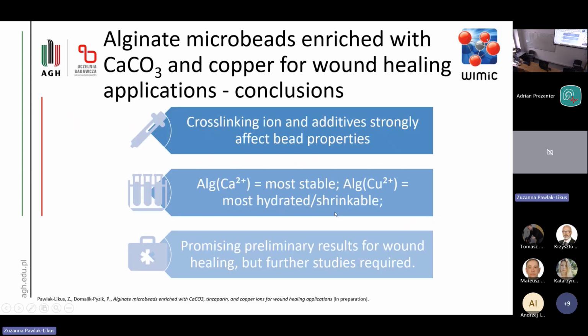So the conclusions that we took from those results are that the cross-linking ion and additives strongly affect bead properties. As we can see, the alginate that was cross-linked with calcium was the most stable, while alginate that was cross-linked with copper was the most hydrated and shrinkable formulation. So those results are promising for wound healing, but of course, further studies are required.